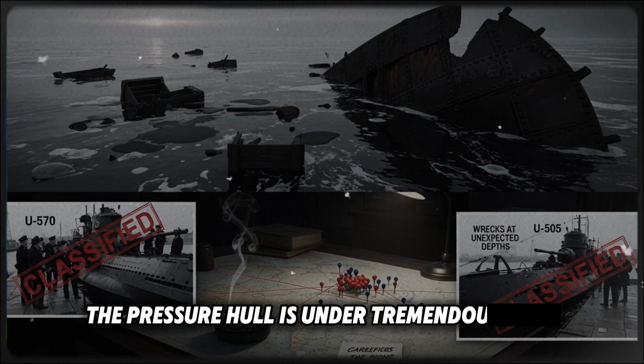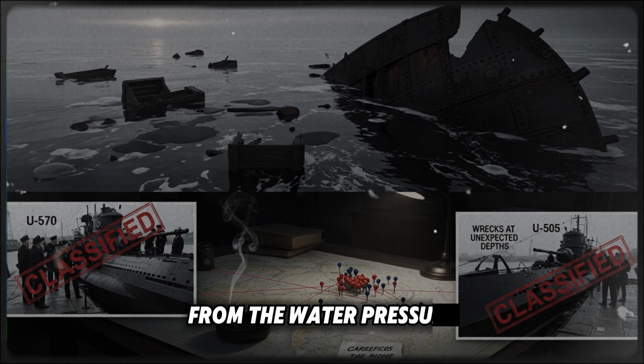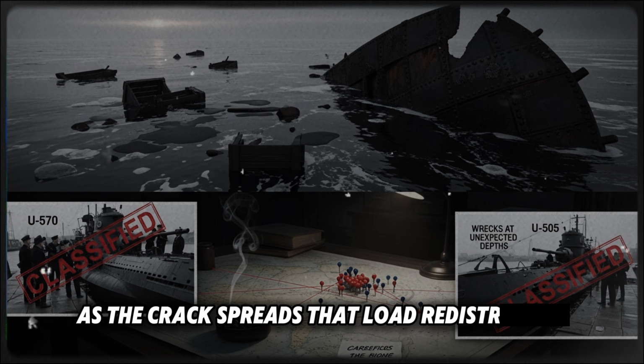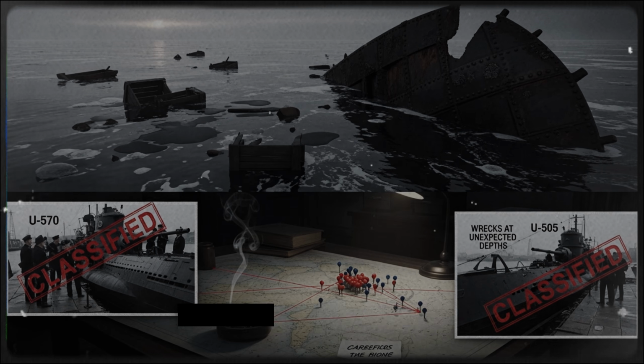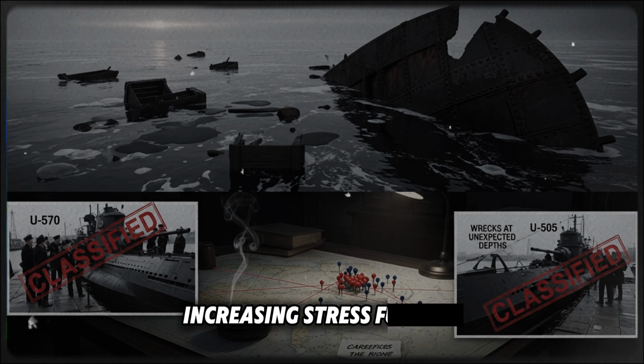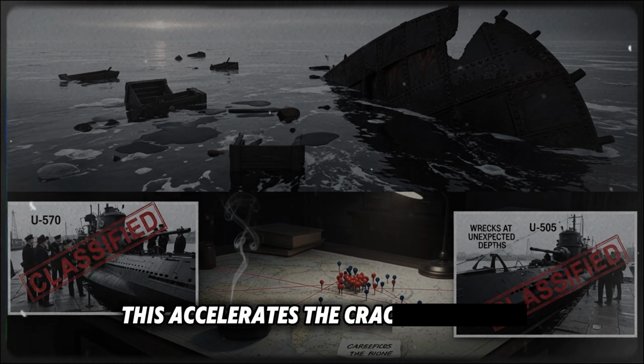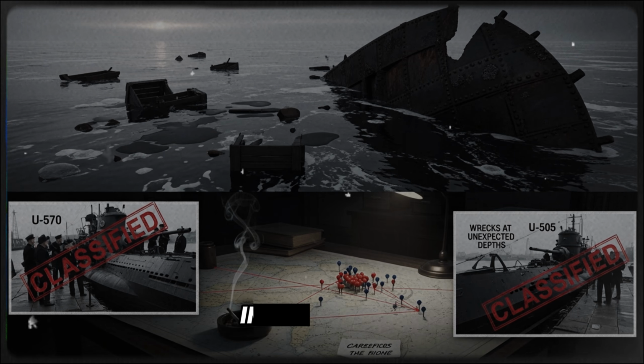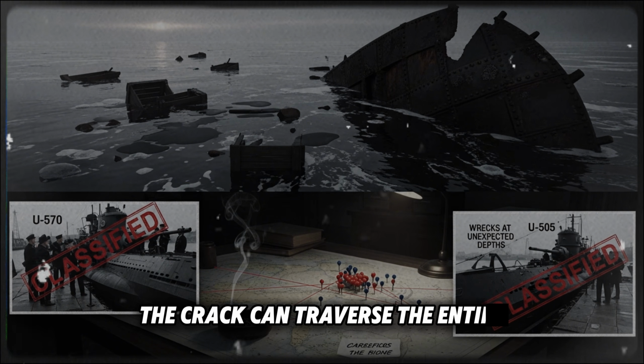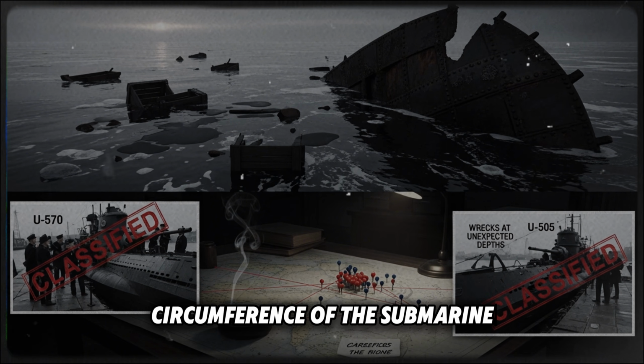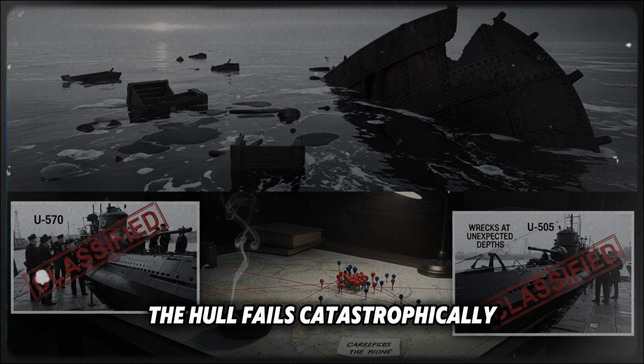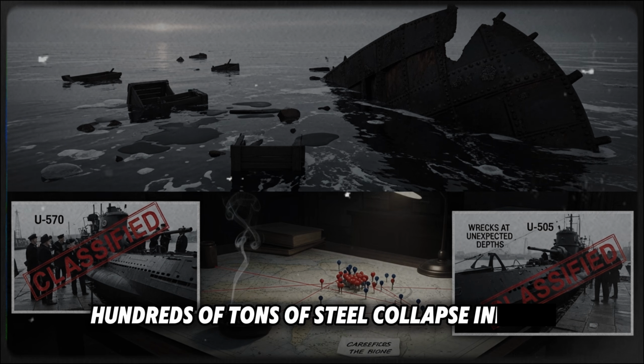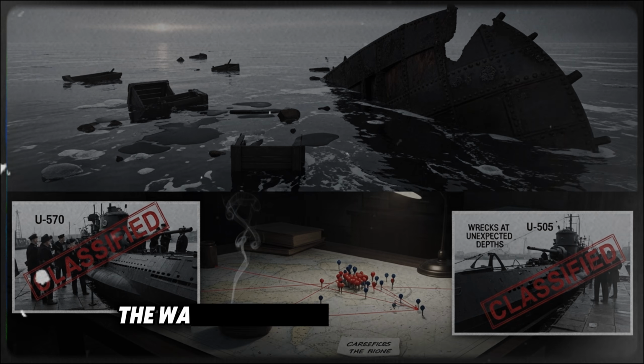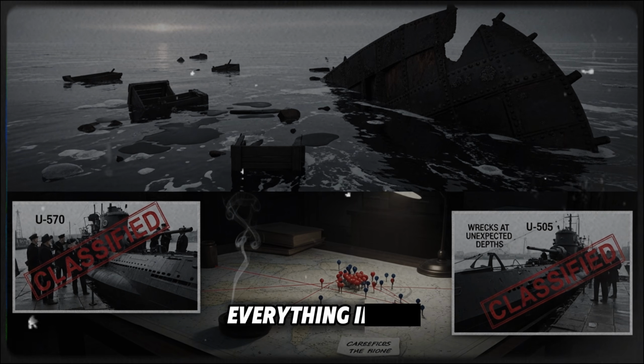The pressure hull is under tremendous load from the water pressure. As the crack spreads, that load redistributes to the remaining material, increasing stress further. This accelerates the crack even more. In milliseconds, the crack can traverse the entire circumference of the submarine. The hull fails catastrophically. Hundreds of tons of steel collapse inward. The water pressure instantly crushes everything inside.